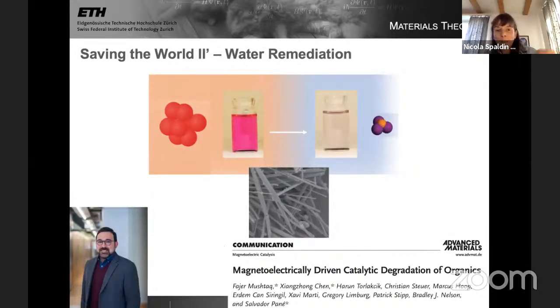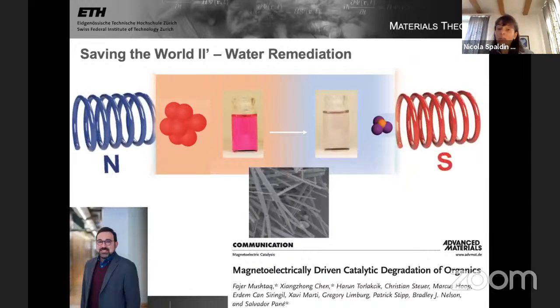The same chemistry can also allow water remediation. This is the work of Salvador Pane from the ETH. And this is some nasty dye, rhodamine B, which is mixed with bismuth ferrite, and it breaks down to small benign molecules. And because of the multiferroic property, you can stimulate this with a magnetic field. So let me stop there.